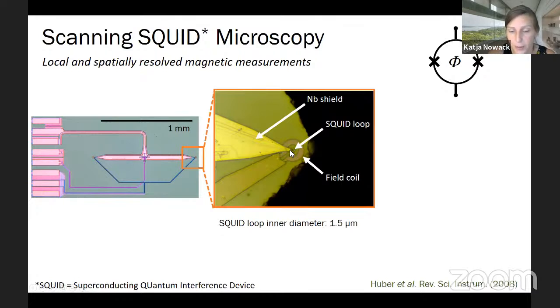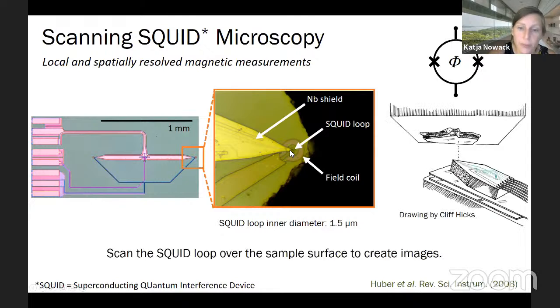This is what we call the pickup loop, which is the loop where we detect the magnetic flux that penetrates this loop. And then there's also an additional coil on chip here, which we call the field coil, and I'll talk about that one in a minute. The inner diameter of this loop is on the order of 1.5 microns in this specific SQUID. That, combined with the height at which we scan, determines our spatial resolution. We take this kind of SQUID and align it under a very shallow angle towards the sample, and then scan it around to create images.